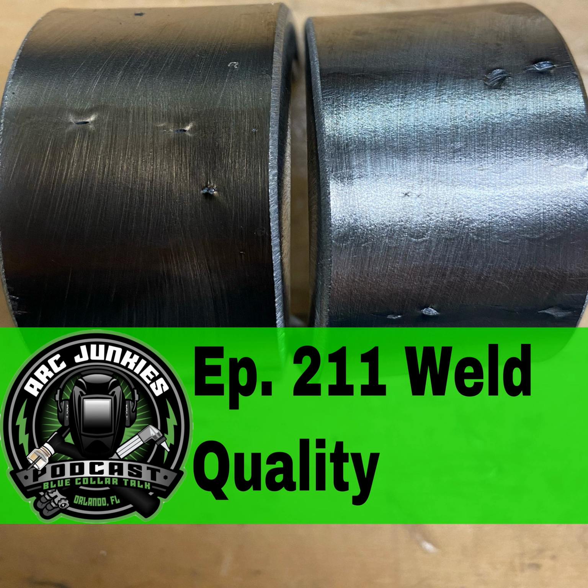You don't want any arc strikes on your material because they create little micro fissures. In a cyclically loaded structure, these little micro fissures can propagate through and start forming crack formations. So we don't want any arc strikes on our material if we can avoid it. Sometimes we can fix this by grinding the surface back off. Sometimes, we're not allowed to use grinders. Arc strikes can cause a lot of problems, so try to avoid them.